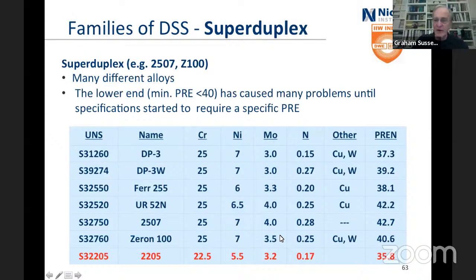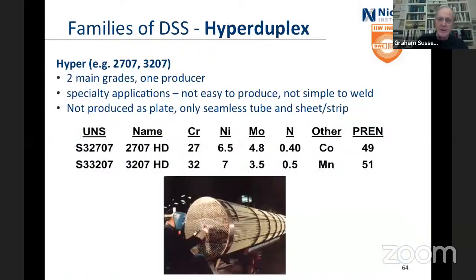25 because it's a 2507. And the PREs are all up here. Now note, here we've got 3 PREs. This minimum PRE is below 40. So technically, and technically with 2205, it won't cope with seawater at ambient temperatures, whereas these do. And quite a few of the specs nowadays, the ASTM, have a column saying PRE to be greater than 41 or greater than 42 or such and like.